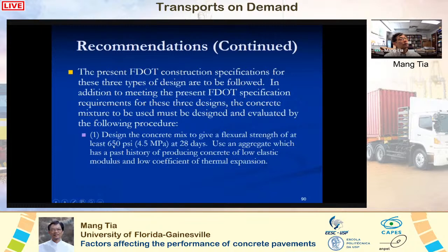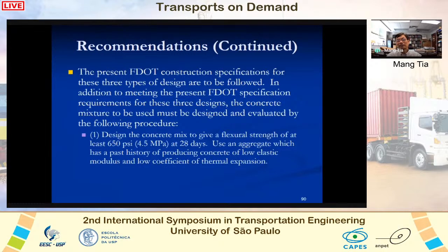Okay, so 650 psi or 4.5 megapascals at 28 days seems to be a good strength to use. The key thing here is to use an aggregate which will give us a low elastic modulus and low coefficient of thermal expansion. How do we know? Well, we can look at past records of test data. If not, we have to run some tests in the lab.